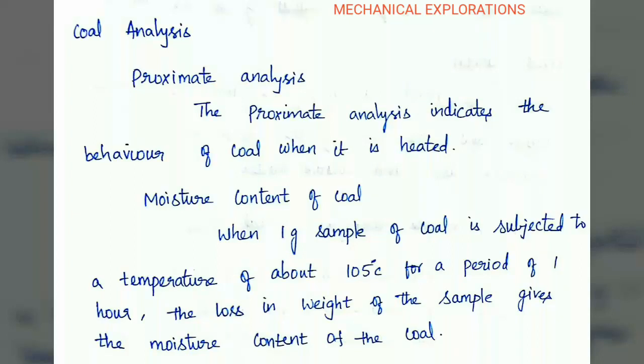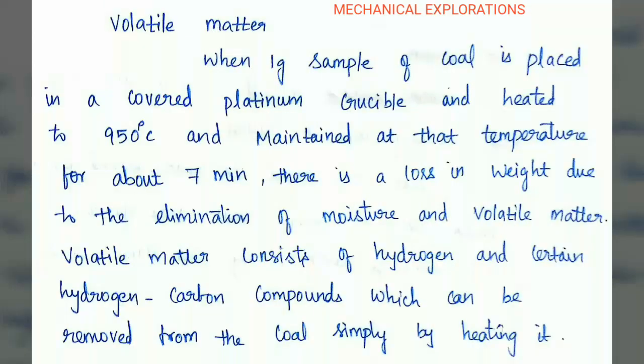Coal analysis — proximate analysis. The proximate analysis indicates the behavior of coal when it is being heated. Moisture content of coal: when a 1-gram sample of coal is subjected to a temperature of about 105 degrees Celsius for a period of 1 hour, the loss in weight of the sample gives the moisture content of the coal.